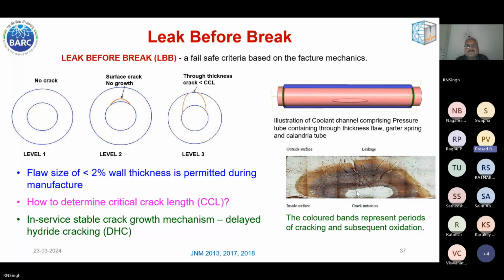So these are size distributions. The hydrides have a particular size range, or peak at a particular size normally? No, it depends on cooling rate. Hydride formation is a hybrid transformation where the zirconium atoms rearrange like a martensitic transformation, and hydrogen is causing interstitial ordering in the transformed matrix. So depending on cooling rate, in fact, in reactor we are getting mostly only delta hydride because of the cooling rate and hydrogen concentration involved. But there are 4 types of hydride: zeta, gamma, delta, epsilon.